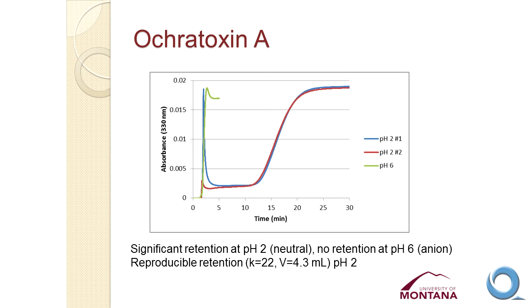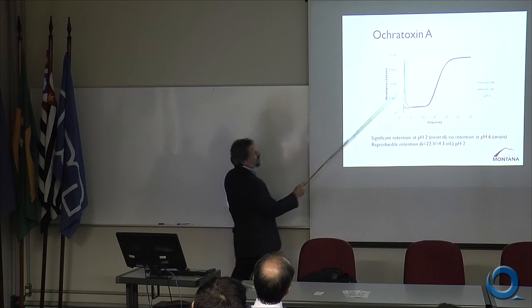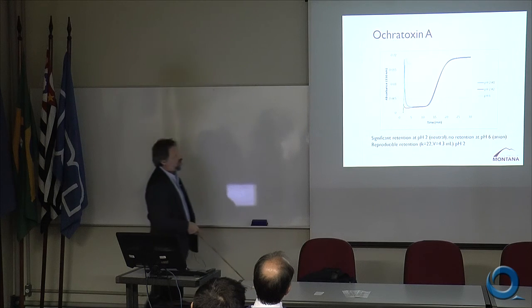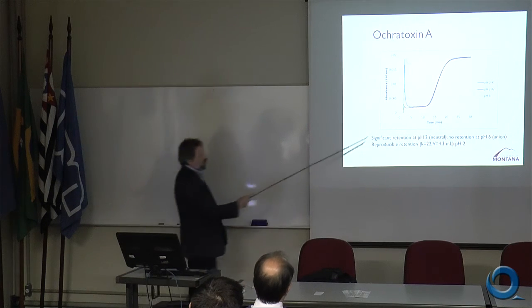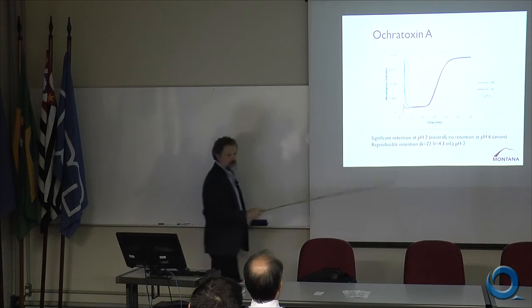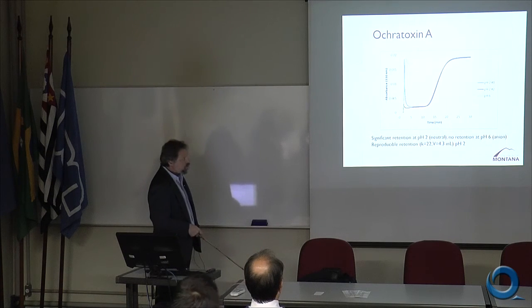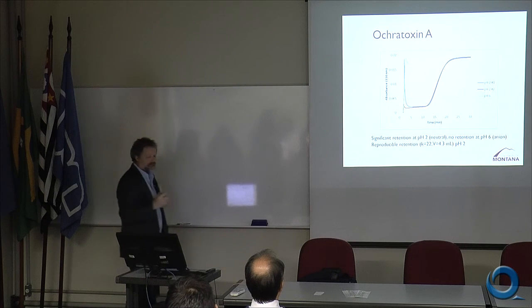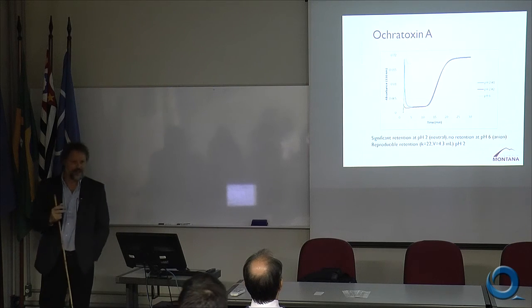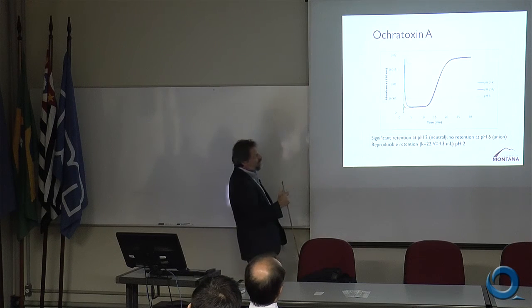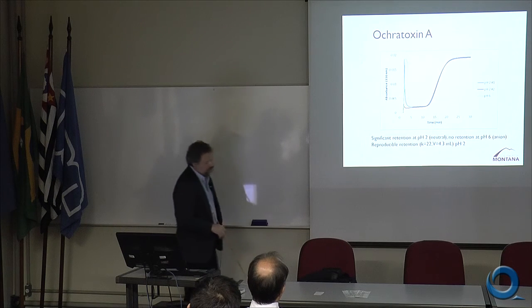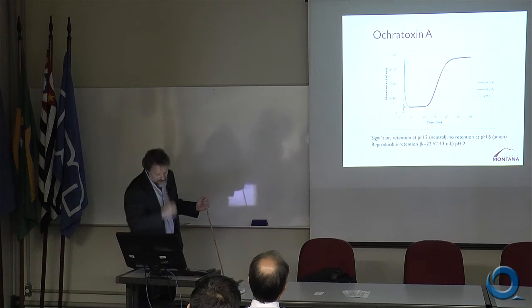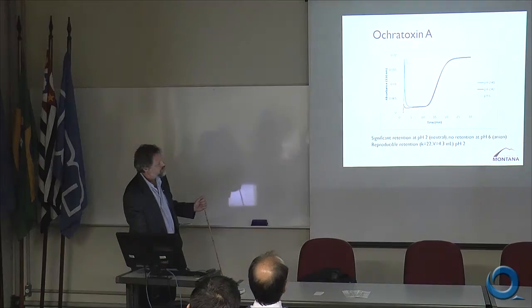But then if we run the same experiment with the same concentration, the same compound at pH 6, where it's anionic, it's simply not retained at all. It just comes straight through right after the injection and stabilizes. So there is no retention of this anionic compound on these cationic nanoparticles, even though it has hydrophobic character. But there's strong retention of the non-ionic compound with that hydrophobic nanoparticle.